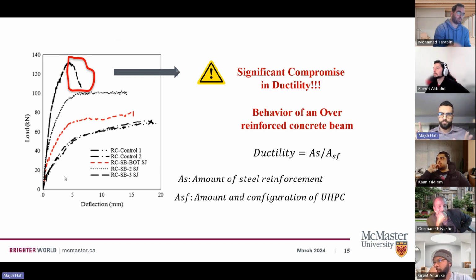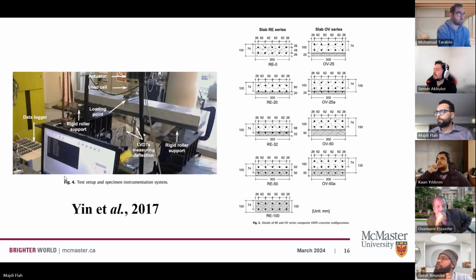Just think about it. When you have a three-side jacket, you have more steel fibers. So it means you have this factor at the bottom. This denominator will be more, so the ductility will decrease. And that's why we don't have any deflection hardening behavior in this curve.